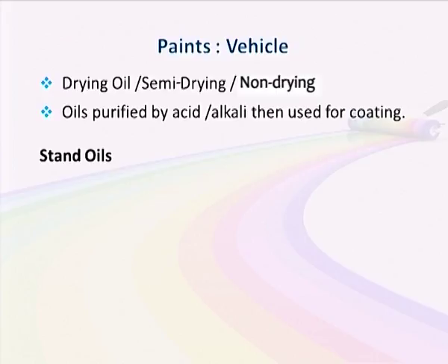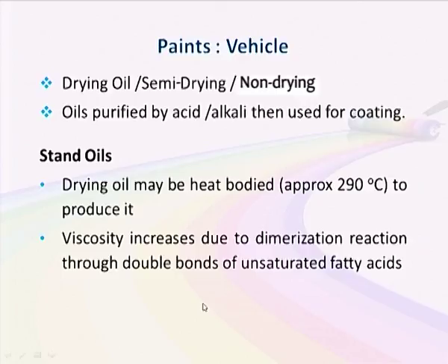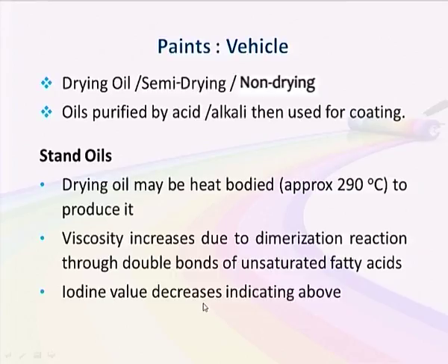Stand oil is also very important. Drying oil may be heat bodied in the range of approximately 290 degrees Celsius to produce stand oil. Viscosity is increased due to a dimerization reaction through the double bonds of unsaturated fatty acids, and the iodine value is decreased.